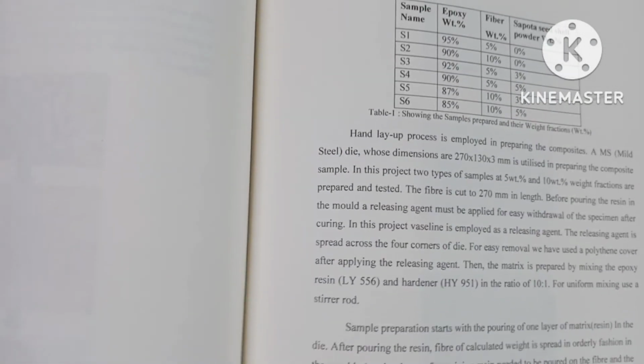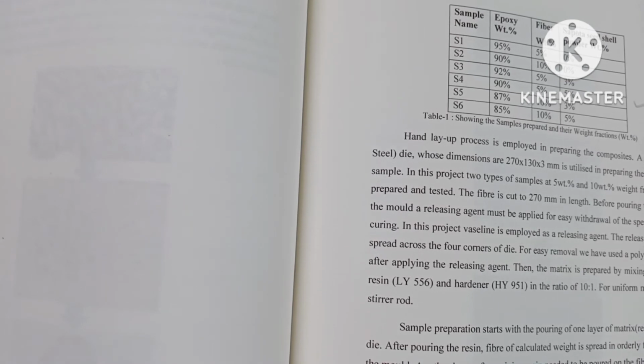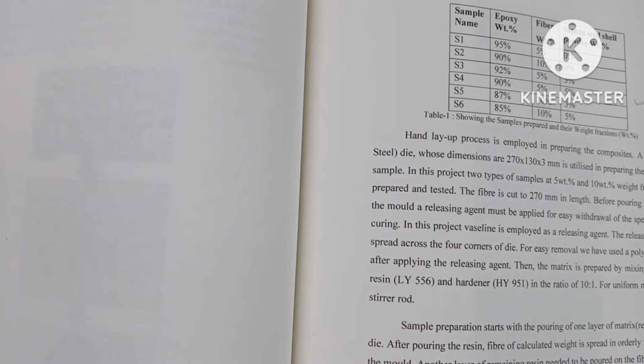We are making a number of different specimens, S1, S2, S3, S4, S5, S6. Each specimen has a different composition of epoxy, fiber, and sapota seed powder. Let us say for the S1 model, the epoxy is 95% and the fiber is 5% only, so there is no sapota seed powder. For S4, 90% is epoxy, 5% is fiber, and 5% is sapota seed powder, and likewise. Six specimens we have to make.